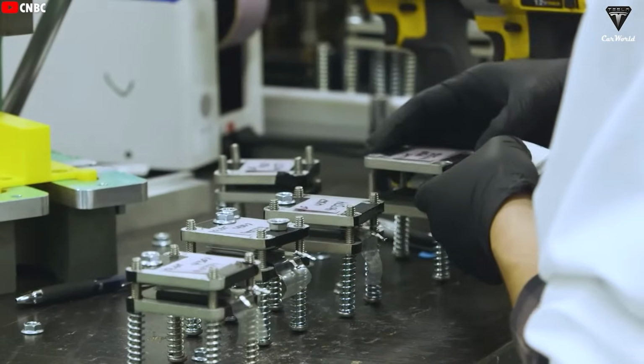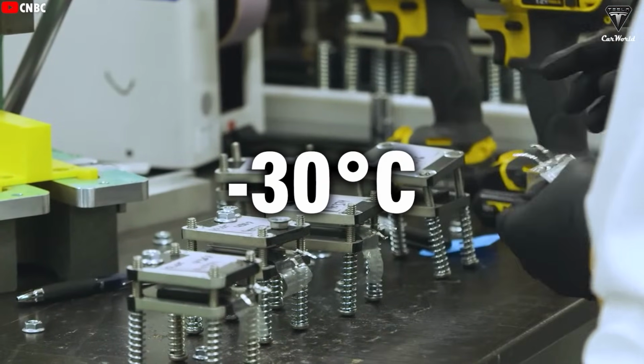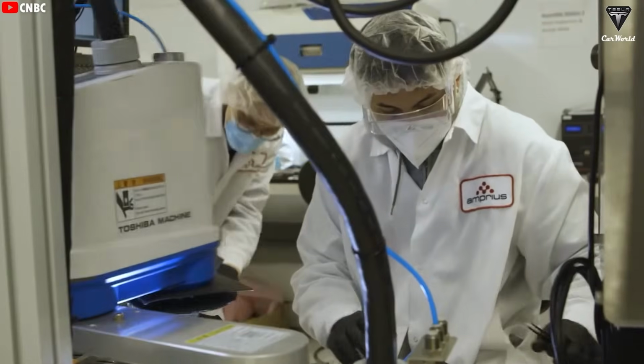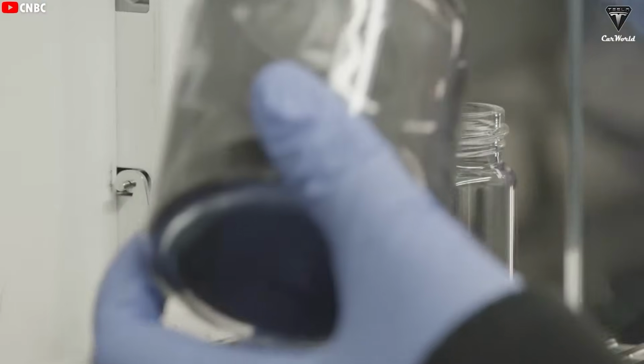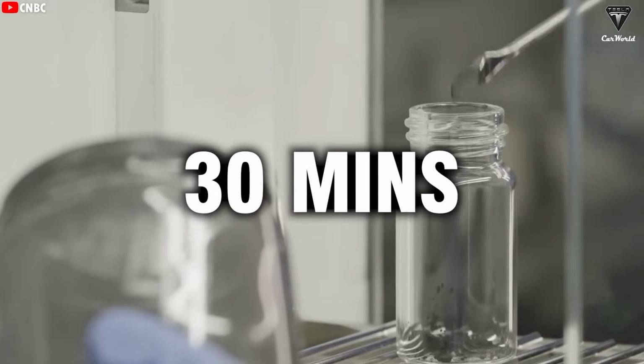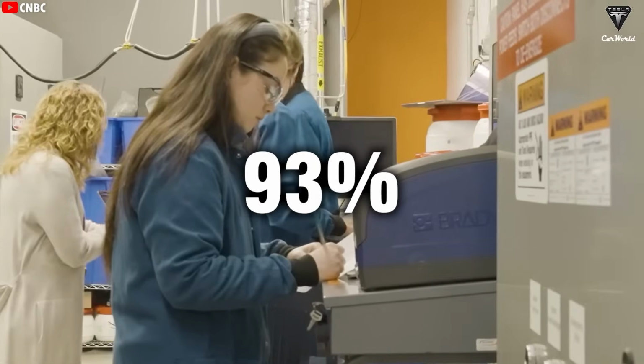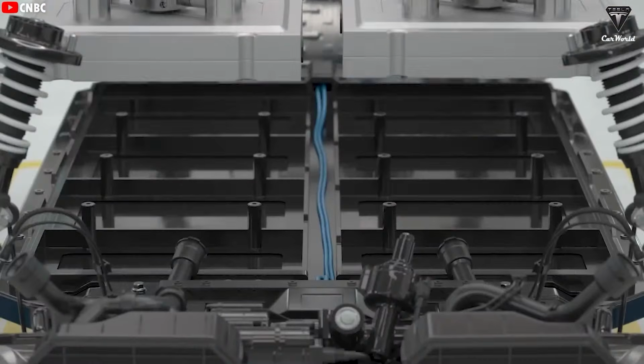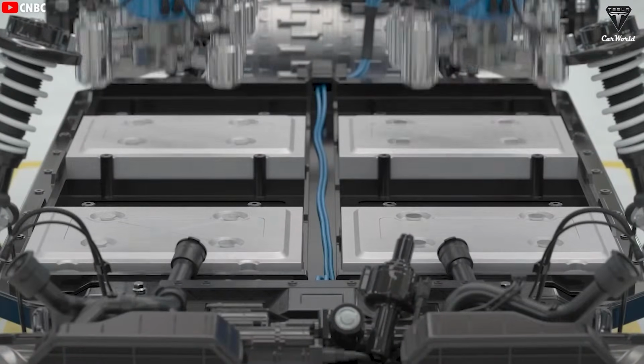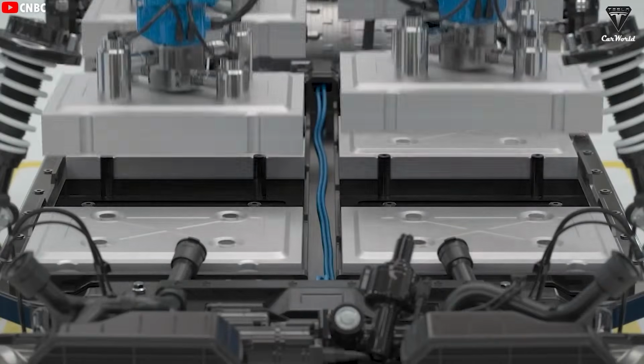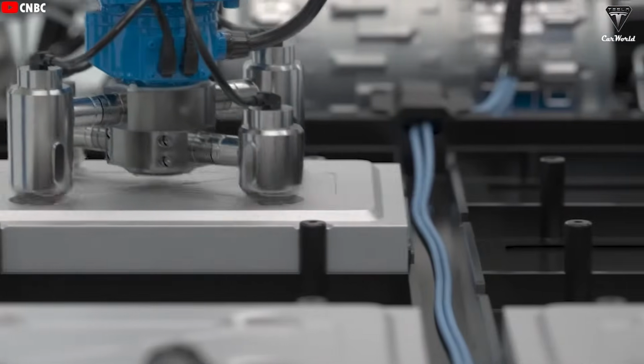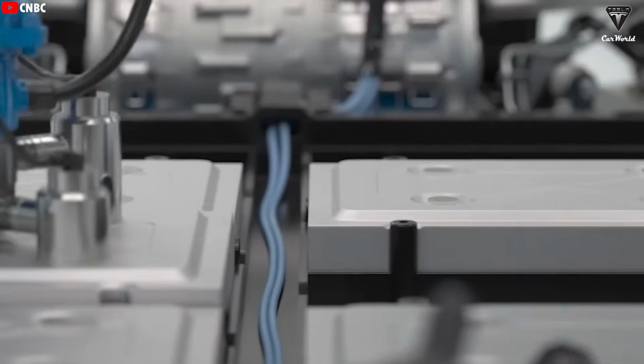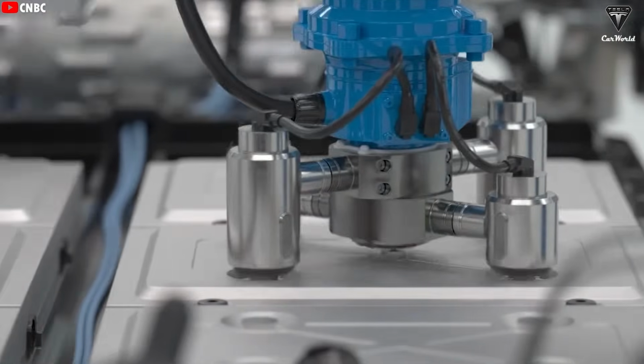In a press release from CATL about their sodium-ion technology, they confirmed similar claims regarding cold weather performance. In lab tests at -30 degrees Celsius, the battery was able to charge from 30% to 80% in just 30 minutes, while still retaining 93% usable capacity. Even with only 10% charge remaining, EVs using these batteries could still drive at highway speeds of 75 miles per hour. Beyond cold weather performance, safety is another major advantage.